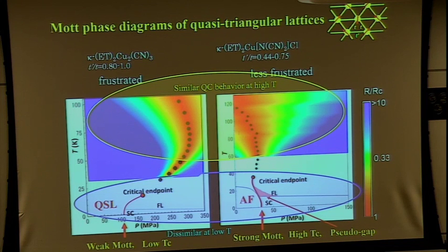Namely, the degree of the frustration of the lattice. So spin liquid appears here, antiferromagnetic order appears here, but TC is lower in this case, while in the less frustrated case TC is higher, 3 Kelvin and 10 Kelvin. And a pseudogap or preformed Cooper pair appears in this material, but not in this one. So very different behaviors appear at low energy scale, reflecting the details of the system.